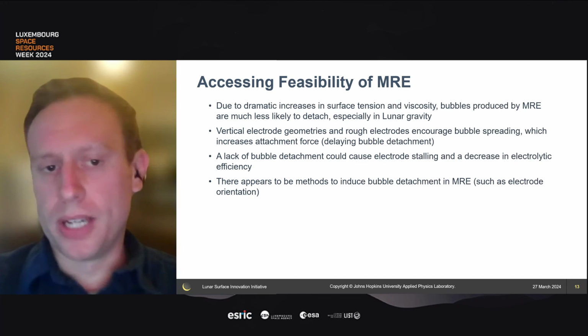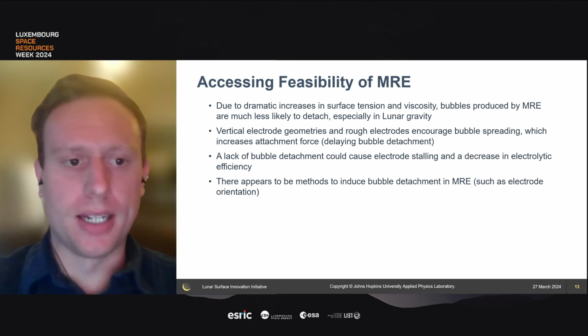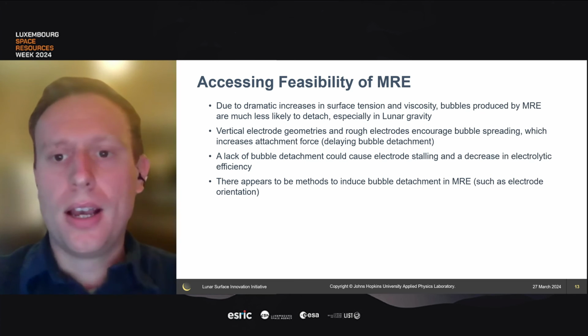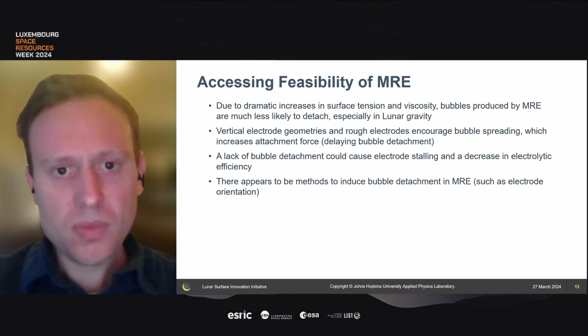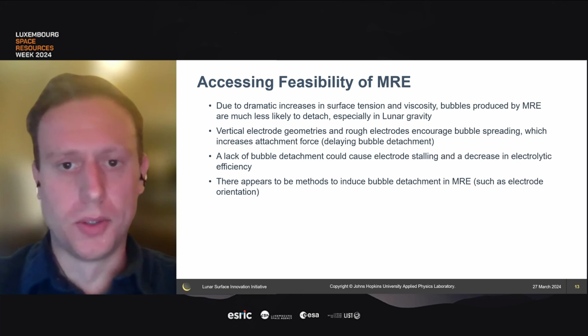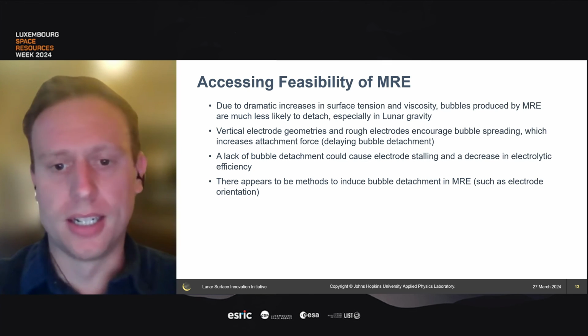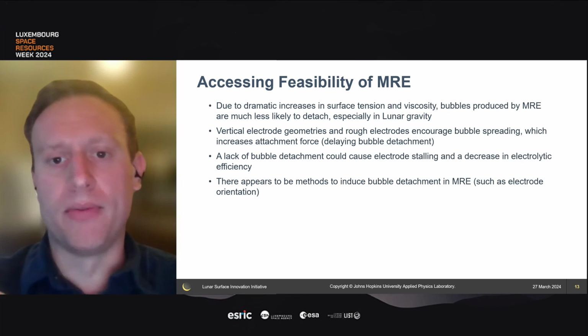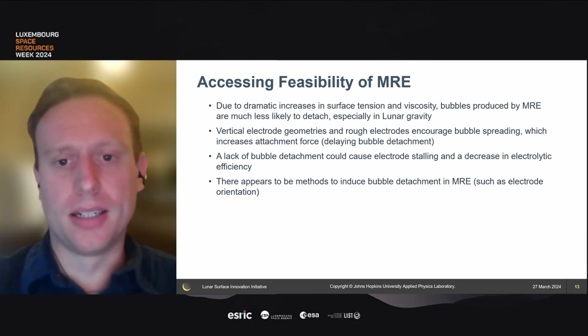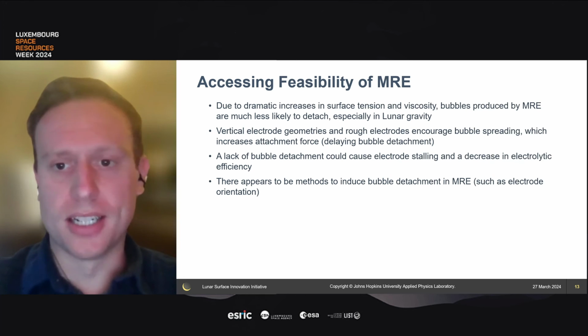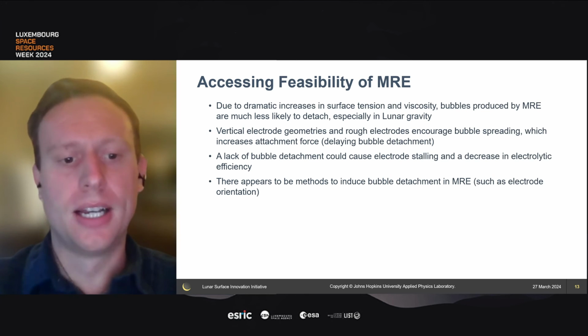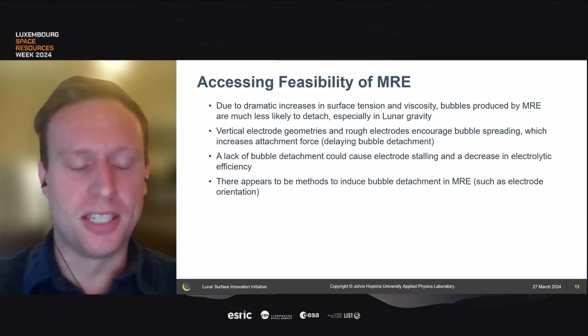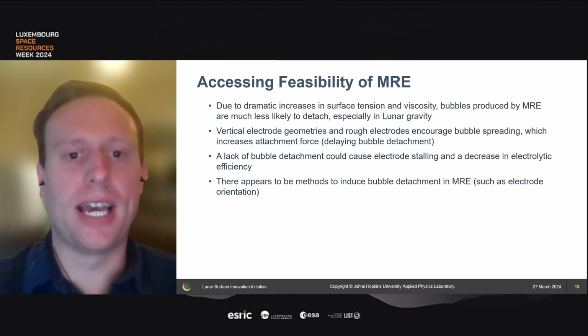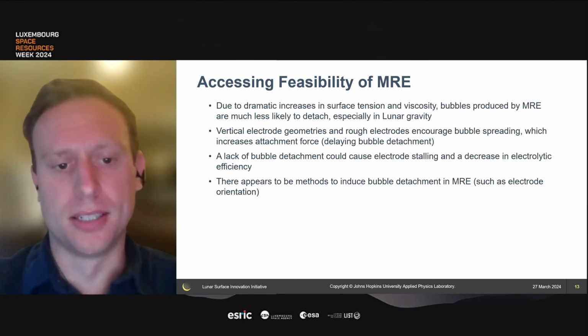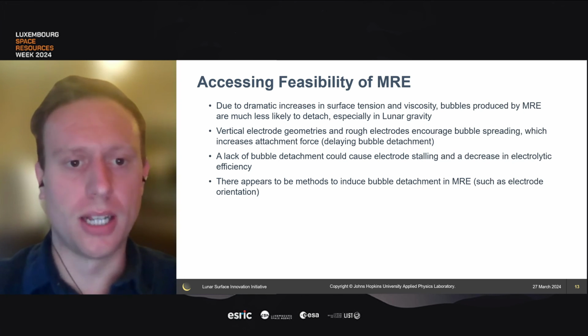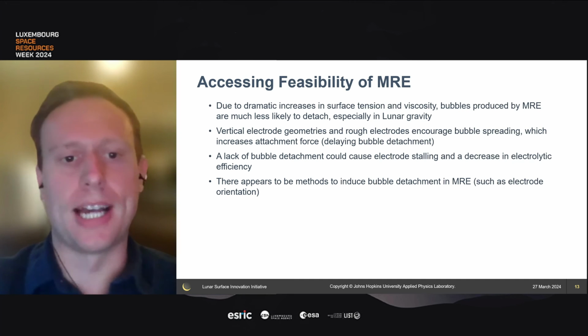So is MRE feasible? We can't answer that for sure right now, but a couple important points to consider. Bubbles in MRE are much less likely to detach, especially in lunar gravity. That's because of the very high surface tension and very high viscosity of molten regolith. As mentioned in the previous slide, orientation does matter, and when designing MRE systems that are actually supposed to operate on a mass scale, it is an important design consideration to orient the electrode in a way that will encourage bubble detachment.